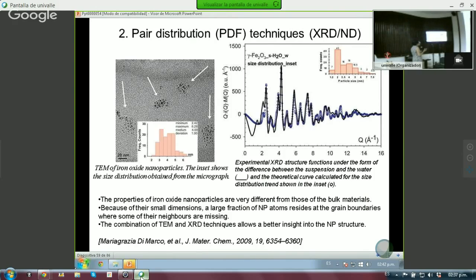And they came to the conclusion that the properties of the iron oxide nanoparticles differ sensitively from those of the bulk materials, which is something one expects. And also, they can locate where these nanoparticle atoms reside. In a way, they can see where they reside at the grain boundaries and where some of their neighbors are missing. And, you know, always having two techniques gives you a better insight into the nanoparticle structure.